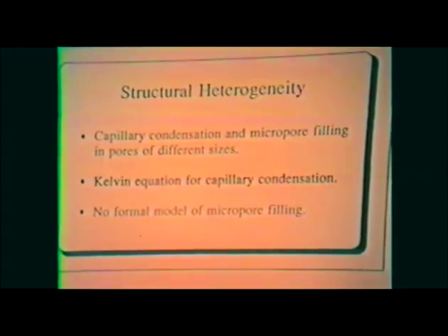We can envisage that you have capillary condensation in mesopores and micropore filling in micropores, obviously, and the nature of the pore size distribution will influence that type of structural heterogeneity. For capillary condensation, obviously, we can use the Kelvin equation to describe that process. But as Roger hinted, there's really no formal, widely accepted model yet for micropore filling.